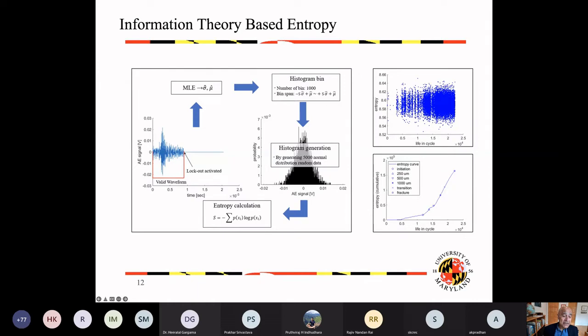Note here that this data are in milliseconds. So in one millisecond, you see this kind of a wave, and this is known as an acoustic signal, or an acoustic wave essentially. And I can easily convert this wave to a distribution, find out the sizes of these from plus to minus, and put them into a distribution function. If I put it into this distribution function, then the Shannon entropy allows me to take this P of xi, which is this distribution, and log of pi, the log of that distribution. It can be converted easily into the entropy.